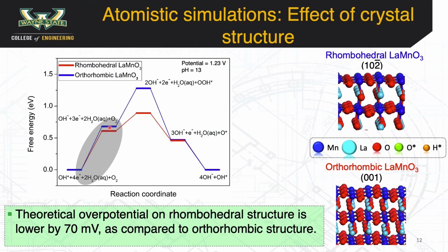The difference in adsorption energetics between the two leads to a 70 millivolts difference in the theoretical overpotential, thus benchmarking our experimental observations. The difference in this adsorption energetics and the theoretical overpotential is attributed to the nature of distortion in the two different crystal symmetries.